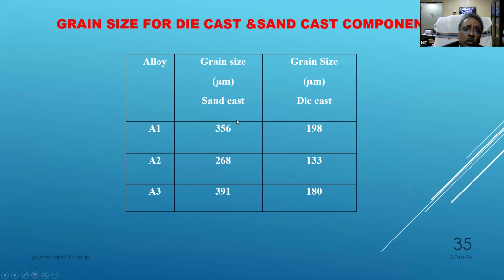You see how this part, A1, is more thick, so in that case the grain size is coarse. A3 is medium, but here the exception is that it is going more, again coarser. A2 is in between in grain size for the sand cast, but in die casting it is giving the best.